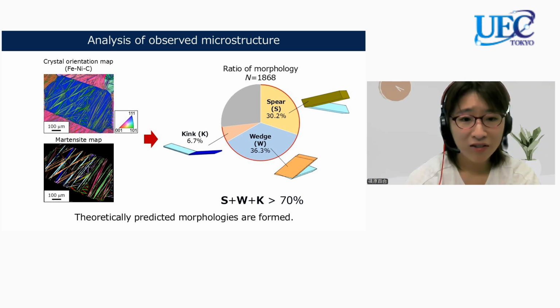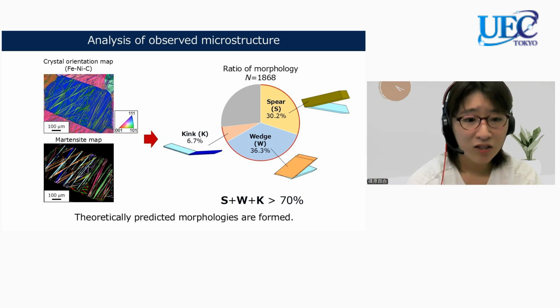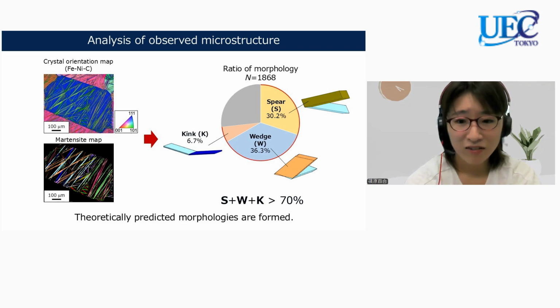We investigate whether the theoretically favorable morphologies are formed in the observed microstructure. This is a crystal orientation map of the martensitic microstructure of an iron-nickel-carbon shape memory alloy. It can be seen that martensite plates are formed in large quantities. Martensite was extracted from this map, and how many times each morphology appeared was counted. Nearly 2,000 pairs were analyzed to obtain accurate results. We found that the theoretically favored morphologies, namely spear, wedge, and kink, accounted for more than 70%.